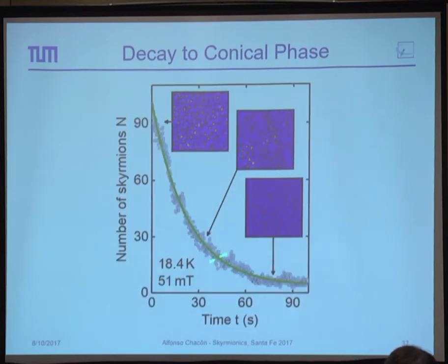And again, we can count skyrmions, and it's important to know that just by changing the field, some part of your sample is already transitioning to the next phase. So it's not like this metastable state is critically metastable until we stop the field, and then it starts to decay. Just by increasing the field, we're losing skyrmions on the way.